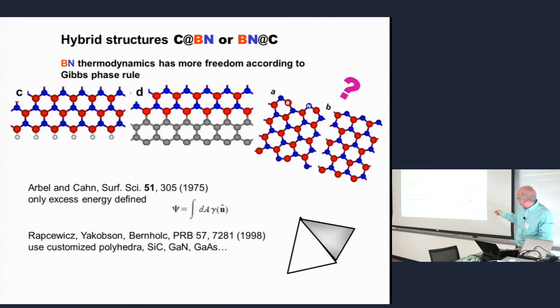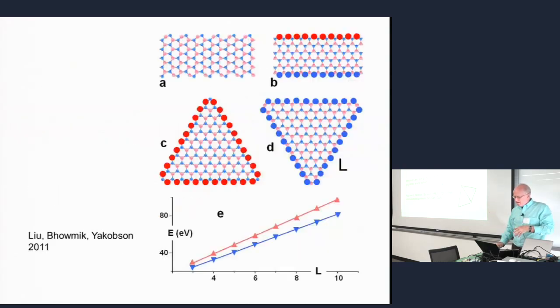So the way we solved this problem a few years ago, it was actually longer before I worked in North Carolina on lone symmetry: you should create a polyhedron, or in this case a polygon of symmetry, such that, if you can, not for all symmetries it's possible, all your edges are identical. So instead of a ribbon, which fails, this is not a good approach. You cannot do it. Although there are papers where they just take the average, but average doesn't make sense, of course. You have to create a triangle, either this way or the inverted one.